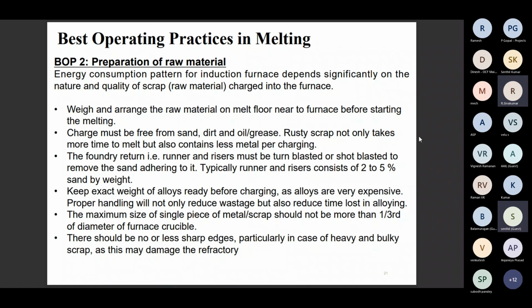The foundry return, that is runners and risers, must be shot blasted to remove the sand. Typically, runners and risers consist of 2 to 5% sand by weight, so it should be removed using a shot blast machine. Keep the exact weight of alloys ready before charging, as alloys are very expensive. Proper handling will not only reduce wastage, but also reduce the time lost in alloying, so that your melt timing period is also reduced.